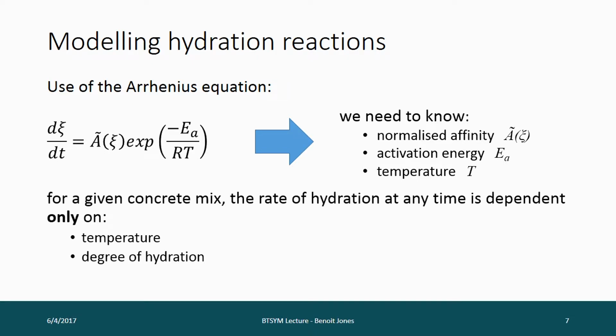So for any given concrete mix, the rate of hydration at any time is dependent only on temperature and the degree of hydration we're at. So if we know the temperature history from the beginning, we can step through time, and in each time step we're calculating the rate of hydration and then calculating the new degree of hydration at the end of the time step and then going to the next time step. And so you can do a time stepping algorithm.